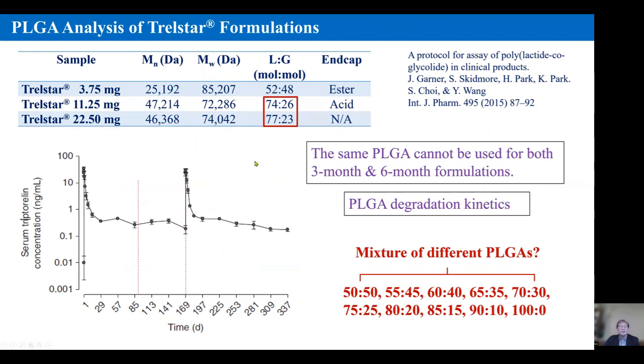But the question is, the 3 months formulation and the 6 months formulation cannot have the same PLGA, because if you simply double the amount of drug, it doesn't mean that you can release twice longer. Okay, the initial burst release may be twice higher, but the duration may remain the same. So the question is, how can you characterize different types of PLGA that may be present in a Trelstar formulation? There we found that